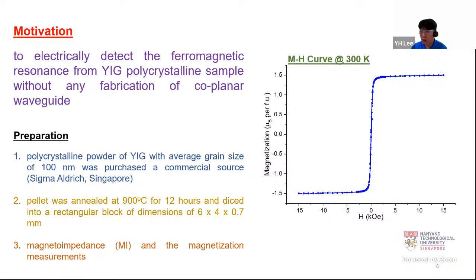We purchased the polycrystalline powder from a commercial source, Sigma Aldrich Singapore. Upon reaching us, I pelletized the sample and annealed it at 900 degrees Celsius for 12 hours. After which I got a rectangular block of dimension 6 by 4 by 0.7 millimeter to do 2 measurements. One, the magnetic measurements at room temperature, the other magnetic impedance.